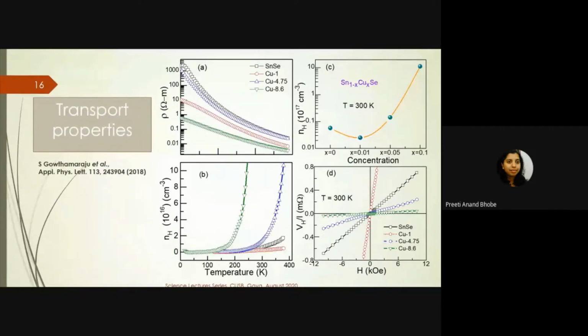The green curve in fact indicates that if I had put a little more copper, then maybe this green curve would go into the next quadrant, and I would have got electrons as my major carrier rather than holes. What it tells me is that, please remember, SnSe is a p-type conductor. As I put in more and more copper, I am putting more and more electrons in the system, and they may be quenching the holes present in the system, and that is what is getting reflected in the change in the conductivity of the material.